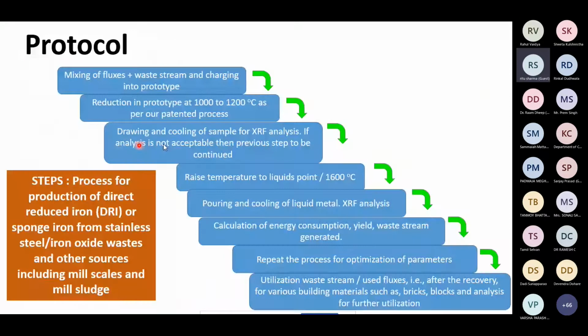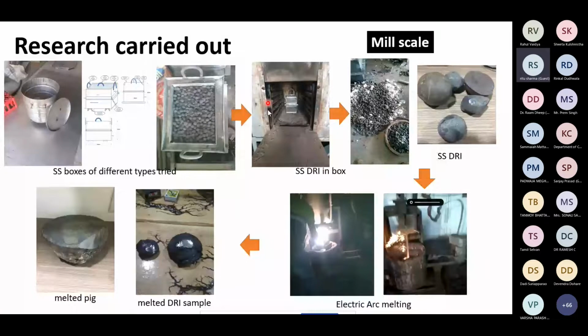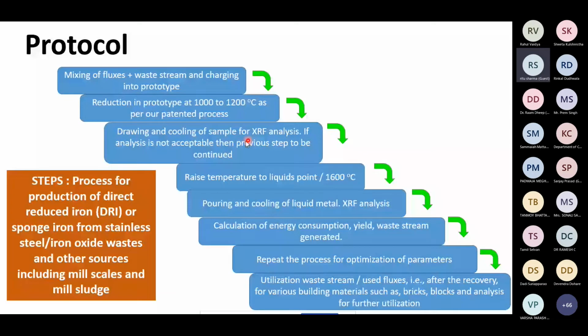Then drawing and cooling of the sample, the reduction in the prototype at 1000 to 1200 degrees centigrade as per the patented process. So this is kept inside the furnace at 1200 degrees centigrade. Then we take the sample and go for the XRF analysis, which gives us the metal composition. Once we analyze it, we can identify what is to be further added. Then we put the material in the furnace again at 1600 degrees centigrade and carry out the XRF analysis again, and then the energy consumption calculations, and repeat the process, and we have optimized these parameters.